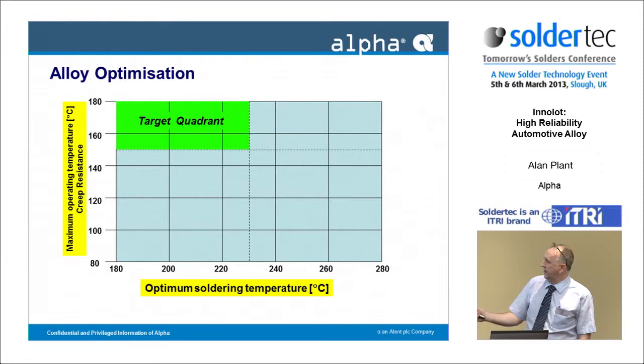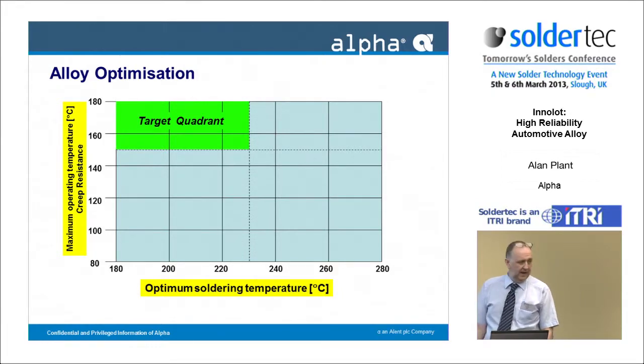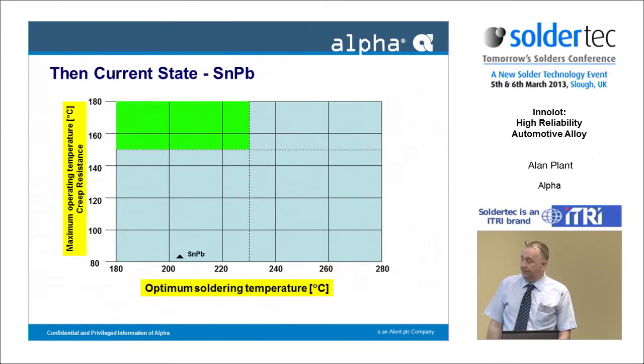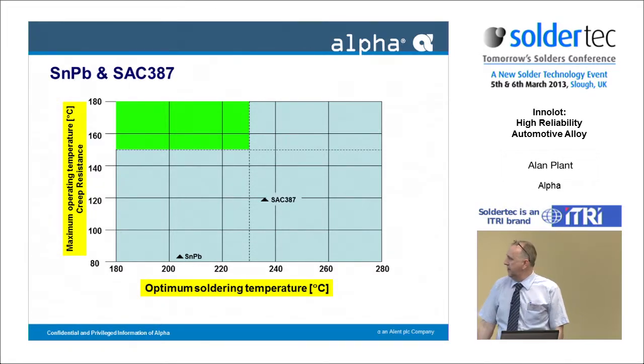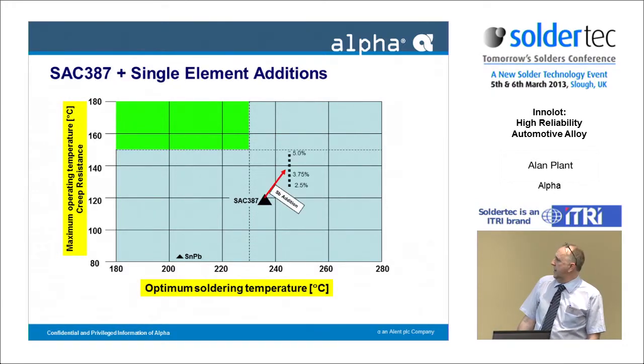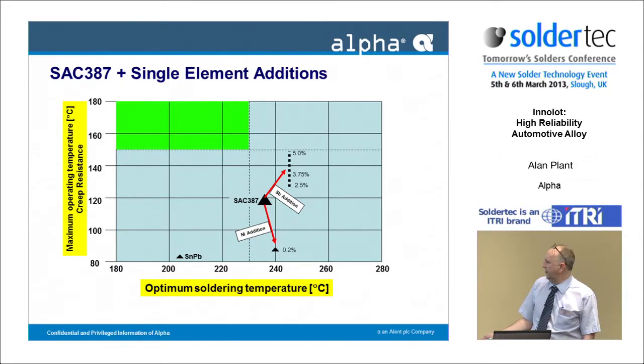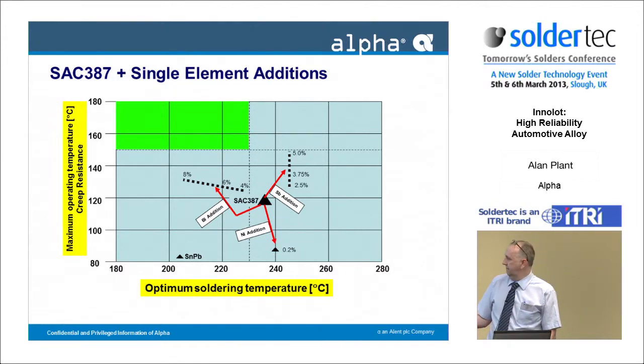And what we were trying to do is get ourselves an alloy that would use those elements but would work up in that target quadrant. So we looked at the single element additions. First of all, we've got our tin lead benchmark down here. We've got our SAC 387 benchmark. So we add ourselves some antimony. Great, it increases the strength, but unfortunately it increases the temperature. The nickel, as we've said before, actually reduces the strength. And the bismuth reduces the soldering temperature and increases the strength.